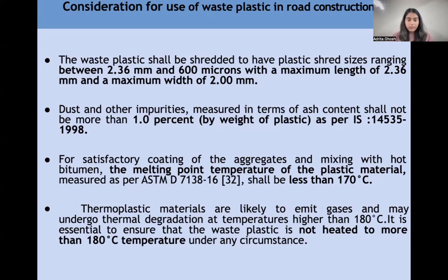1998. For satisfactory coating of the aggregates and mixing with hot bitumen, the melting point temperature of the plastic materials, measured as per ASTM D7138, shall be less than 170 degrees centigrade.